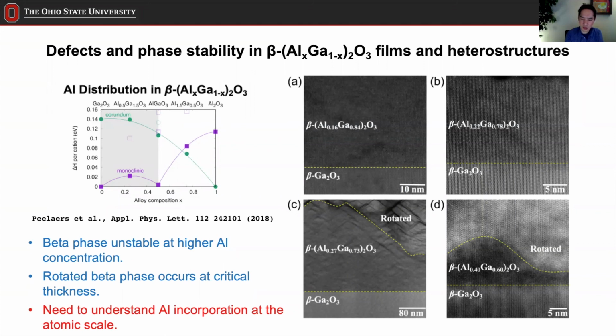Although I didn't really elaborate on it, there can be some effect of strain as well, because if you increase the aluminum concentration, it's not just whether the phase itself is stable or not, but also how much strain is building up from the substrate. So I think both matter for the stability of the phase, and that eventually determines how far it can go when it's being grown.